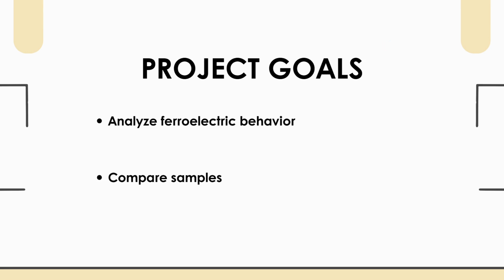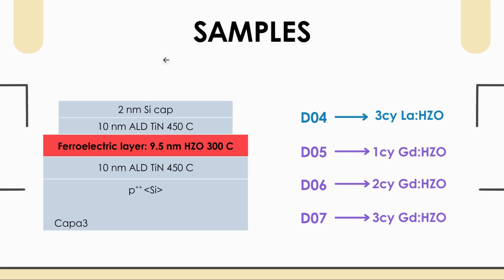My main goals were to analyze ferroelectric behavior, to measure how fast and how much they switch using PE loops, PUND measurements, and NLS fitting plots, and then compare different doped hafnium zirconium oxide samples. In this project, I tested 4 samples, D04 to D07. The figure shows the device's basic structure.